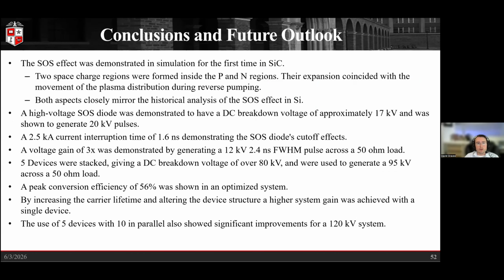So to conclude, one of the biggest takeaways from this was the SOS effect was demonstrated in simulation for the first time in silicon carbide. With this, we saw the distinct two space charge regions that were formed inside the P and N regions, with their expansion coinciding with the movement of the plasma distribution during that reverse pumping phase.